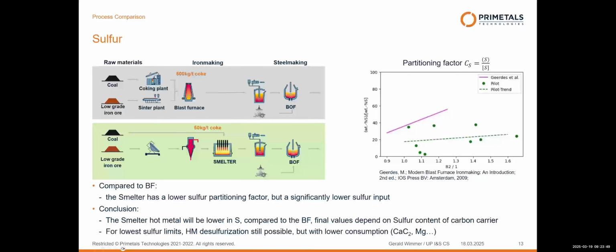Second point is sulfur. How does the hot metal from the smelter compare to the hot metal from the blast furnace? And of course, not a lot of sulfur is in the iron ore. Sulfur is mainly coming from the carbon, meaning the coking coal or pulverized coal we inject, that we add to the process. And that's a big difference. On the blast furnace, we need about 500 kilograms of coke per ton. On the smelter, we need, as I've shown in the last slide, depending on the direct reduction plant, natural gas based or hydrogen based, but typically we start at some 50 kilograms per ton. So we have about 1/10 of the carbon that we add to the process, meaning the sulfur input is also only 1/10.